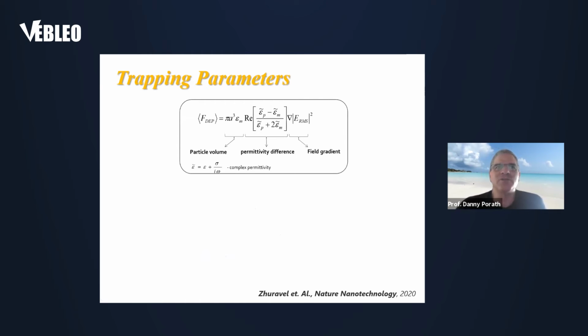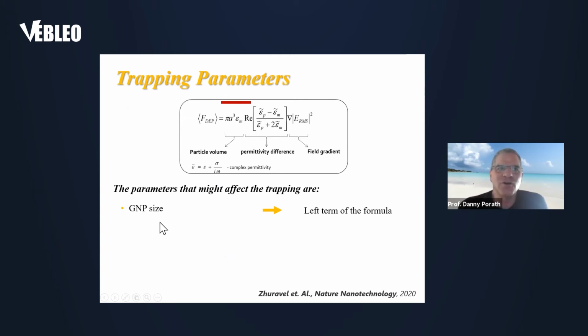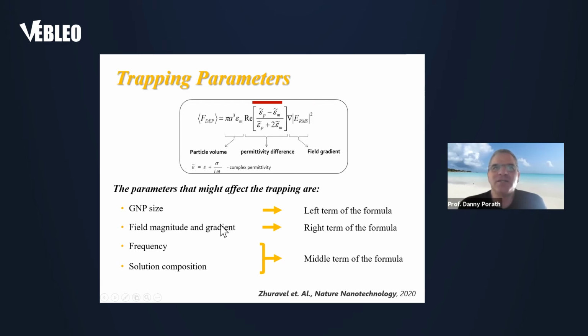I will not go into all the details, but the left term includes the radius of the nanoparticles, so that's the size of the nanoparticle. The right-hand term refers to the field magnitude and the gradient that is applied, and the middle term tells us the dependence on the frequency and the composition of the solution. So in this way, we can control all the parameters that are needed for the trapping.